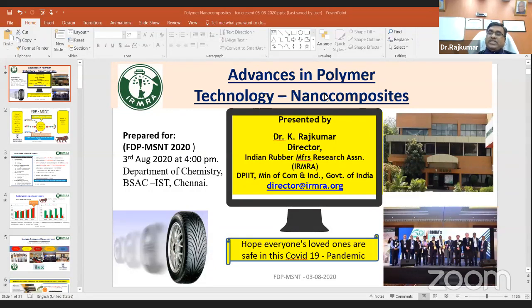So basically, that's the problem with this method as such. I have been telling, if it is a thin layer of casting, the solvent gets evaporated and it's good. Whereas if it is a thick article, then there is a possibility of solvent being trapped. So you need to optimize the drying temperature, and ensure that a constant weight is reached. So these are the methods.